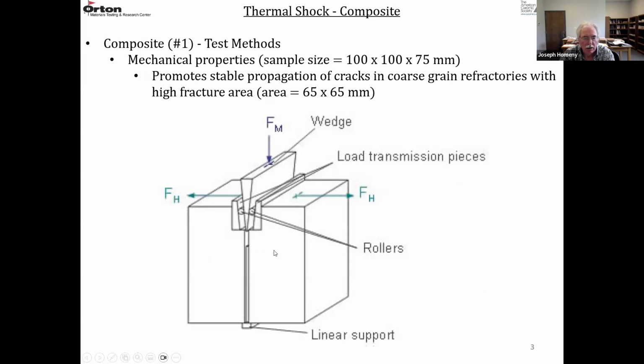So this is the wedge splitting test. You have to put a notch in this material. You put these transmission pieces in that notch. You have two rollers, and then the wedge forces the rollers apart and causes the crack to move downward. So there's a vertical force, and then the wedge creates these two horizontal forces. This test promotes stable crack propagation in these coarse grain refractories. The fracture area is pretty high.